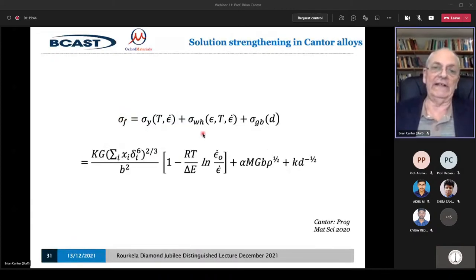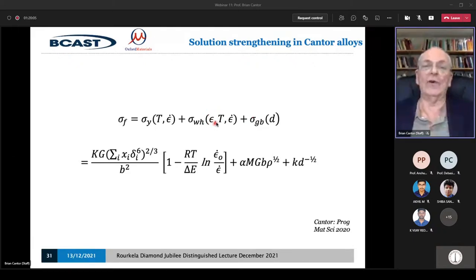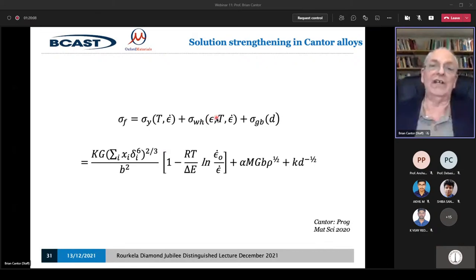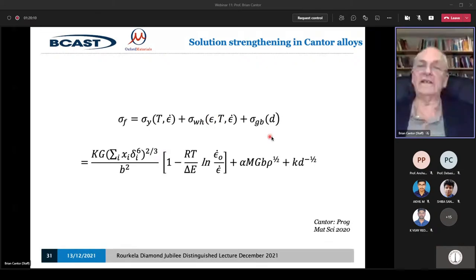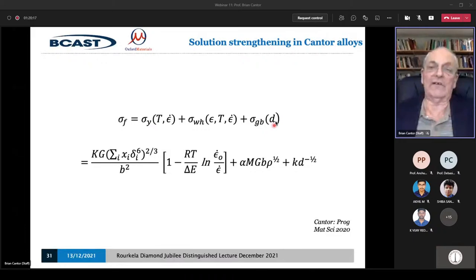And this is the theory. I'm not going to bore you with the details of this theory, but the strength of a material like this, of a strengthened metal, depends upon three components. It depends upon the difficulty of moving the dislocations in the first place. That's the thing that's changed. There are two other effects, what's called the work hardening. The dislocations interact with each other. That's called work hardening, and they change the strength of the material. And then the dislocations also interact with grain boundaries, or boundaries between crystals, because materials are very often polycrystalline.